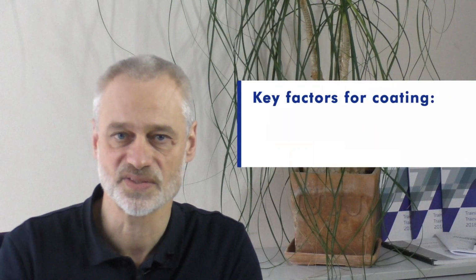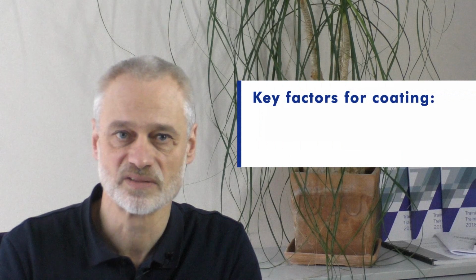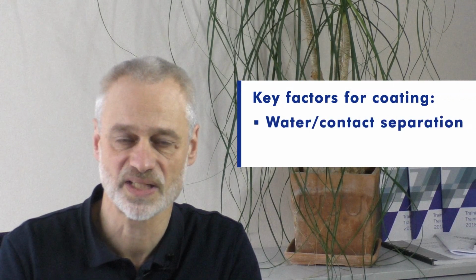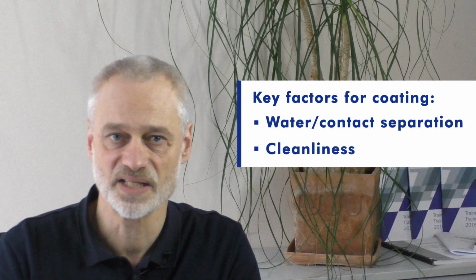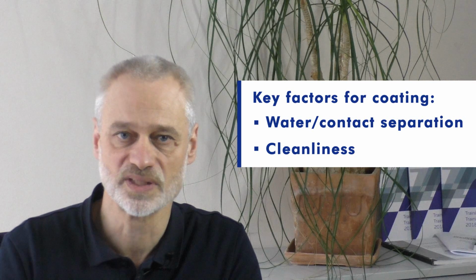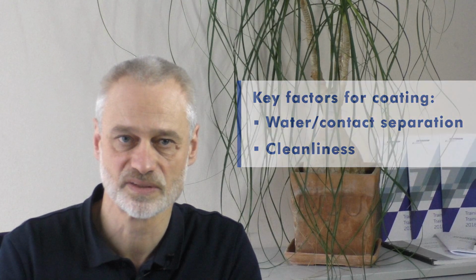So, how can we avoid ECM? One option is coating assisted by cleaning. The coating isolates the condensating water from the electrical potential and breaks the mechanism of water electrolysis. Cleanliness is necessary for a sufficient bonding of the coating to the metal surfaces. Otherwise, there would be water condensating beneath the coating and thus a bypass of the protecting effect.